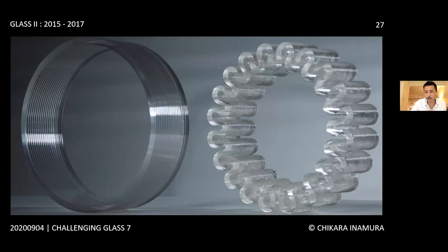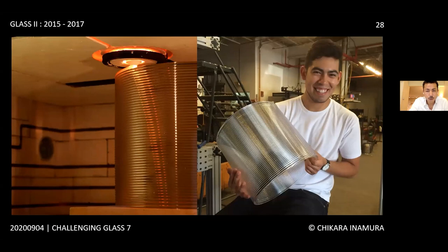With this, we achieved a consistency across a greater range of curvature and precision. Glass is hard and brittle, and the lack of ductility makes it prone to stress concentration. The ability to produce a consistent and reliable wall thickness across a range of curvature ensures that we can minimize such stress concentration. We also achieved precision at significantly greater volume. The new printer is capable of producing glass at a maximum of 1 cubic foot in volume and 20 kilos in mass. Speed-wise, it prints approximately 7.5 kilos per hour.